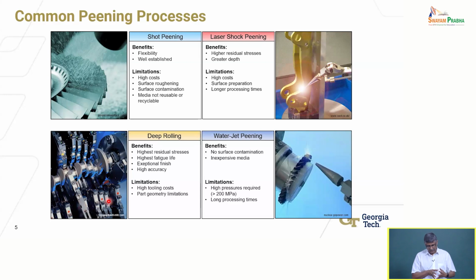So, laser shock peening, depending on the strength of the shock wave that can be generated, can produce deeper stresses, which can be a good thing depending on the application, where that material is being subjected to loads that produce stresses much deeper into the material. Compressive residual stresses deeper into the material extend the life of that component and prevent failure from occurring due to tensile loads. But it's a higher cost process. You need a laser system. You need to prepare the surface. In the example that Professor Samuel showed, you need to submerge this in a medium.